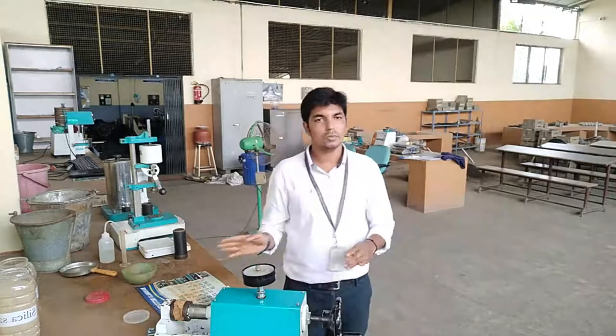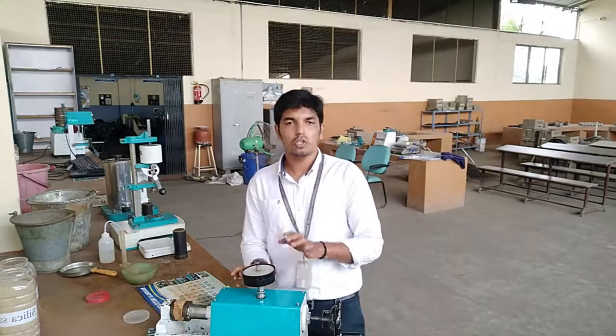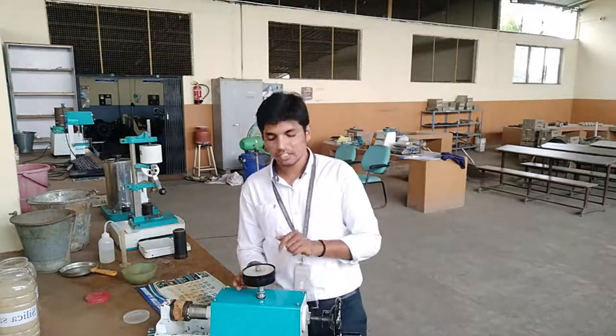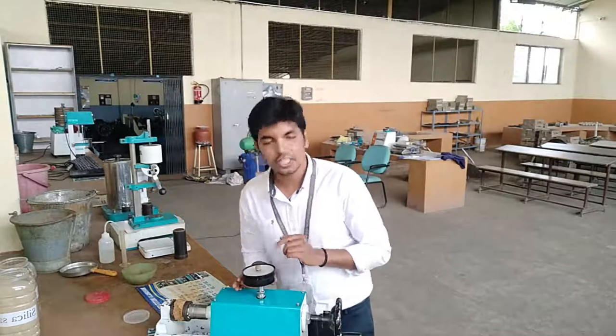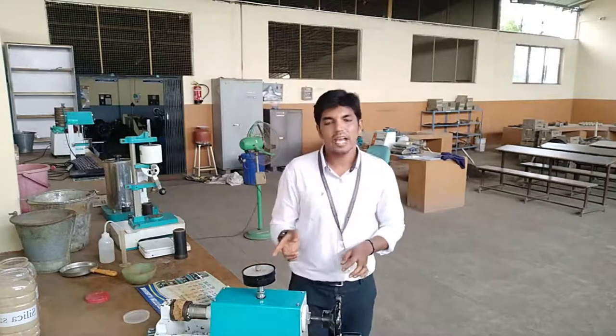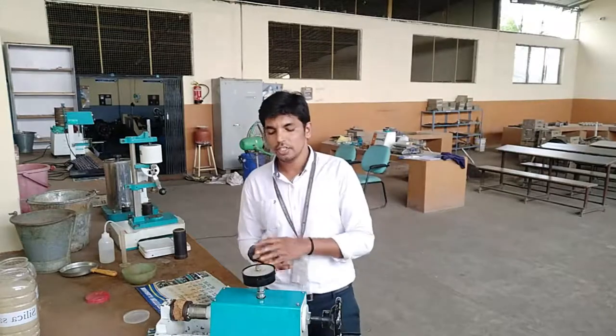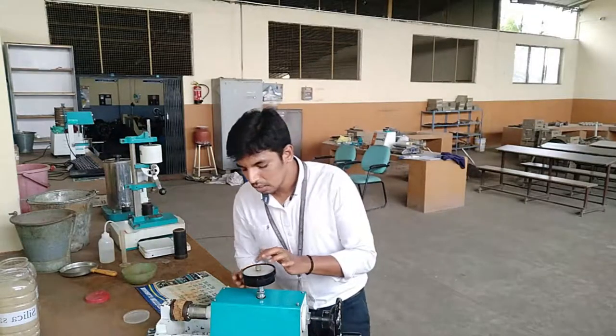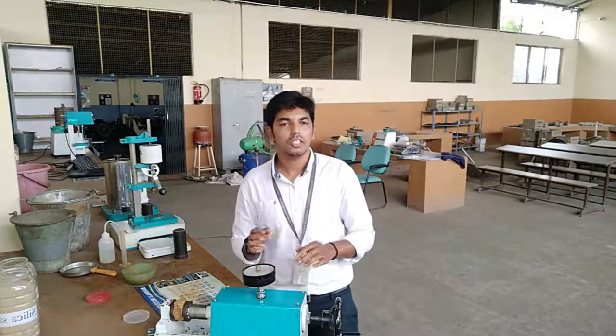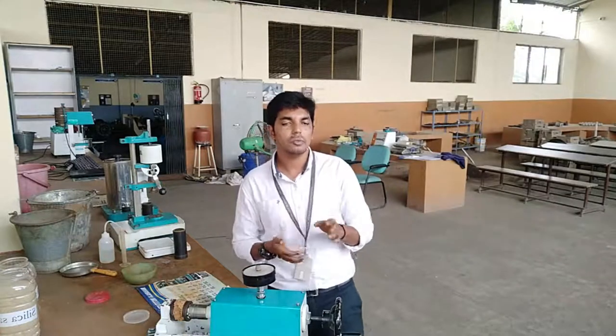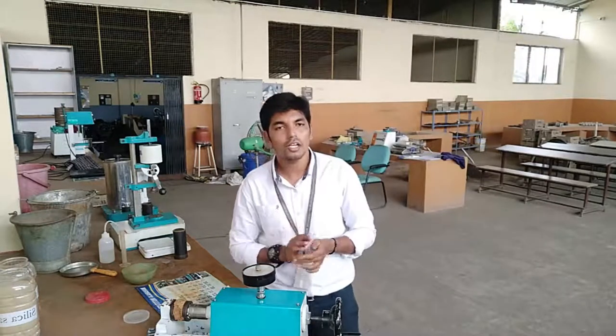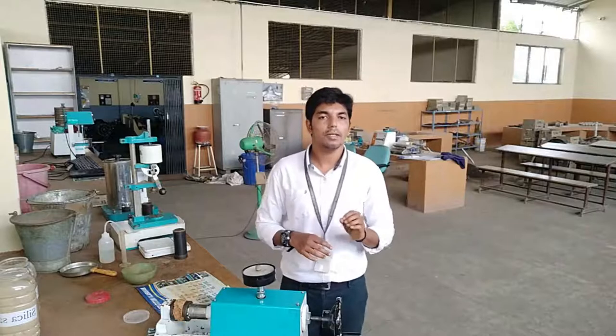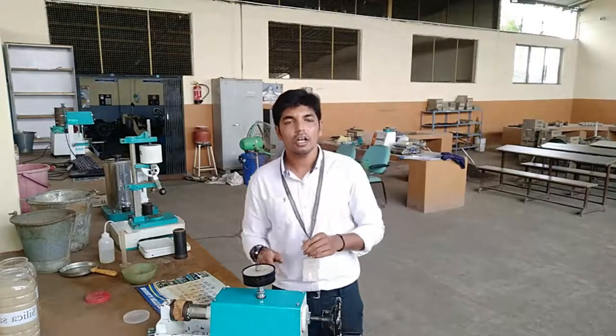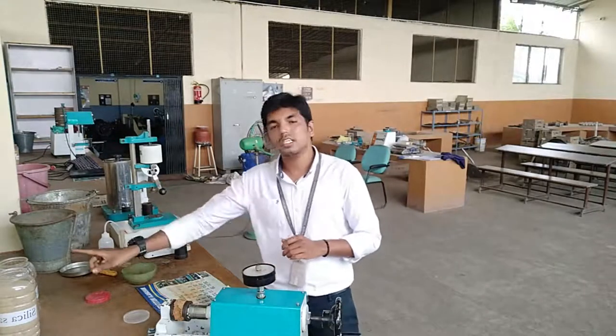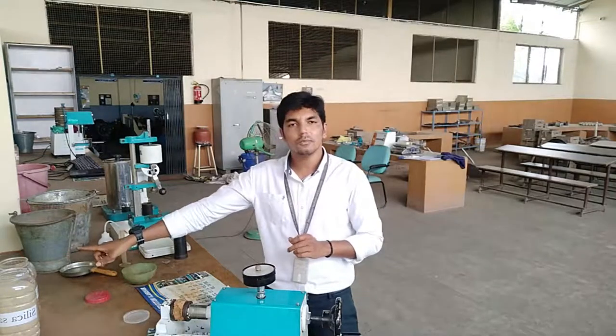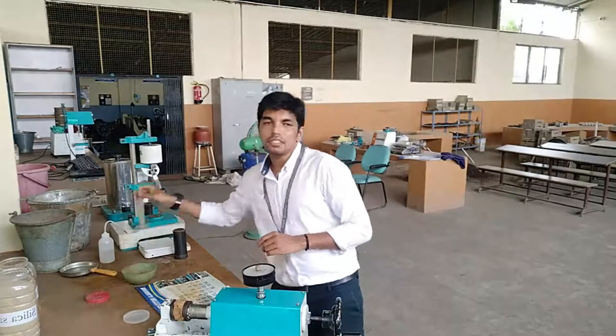So now the specimen has completely failed. Then note down the final dial gauge reading on the shear scale. On the shear scale, the black reading shows between 38 and 40. So I can take 39, that means 0.3. So 0.3 into 100 shows 30 gram per centimeter square is the shear strength of the molding sand, having silica sand of 135 grams, 15 grams of clay binder and 15% of water.